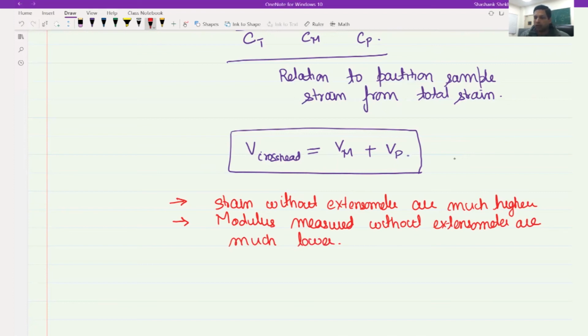In fact, in one of the recent labs that we are doing in our campus, in the mechanical behavior lab, we measured the elastic modulus for aluminum samples, and it came out to close to 12 to 13 gigapascal, when the modulus for aluminum is close to 60 gigapascal, somewhere between 60 to 65. So you can see that elastic modulus becomes so much lower. Of course, this is very poor quality data. If we refine it, we can get much higher modulus, but still it will be lower than the actual value that you expect, which is close to 60 to 65 gigapascal.